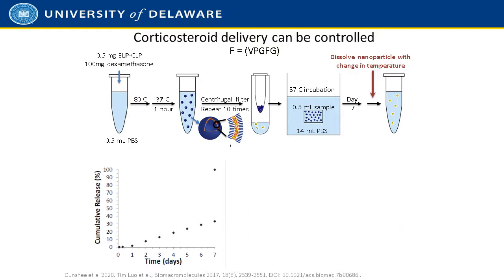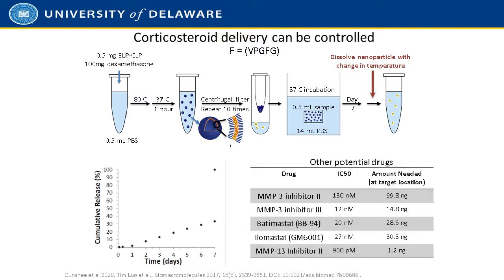This is release of dexamethasone, which is a corticosteroid that's commonly employed to address symptoms in osteoarthritis. The drug release of the dexamethasone is linear up until day 7, and when we trigger dissolution of the nanoparticles with temperature, the rest of the drug that's encapsulated is released. So that gives us opportunities to localize not only dexamethasone, but also other small molecule inhibitors that are in various stages of the clinical pipeline for treating osteoarthritis symptoms or the progression of the disease.